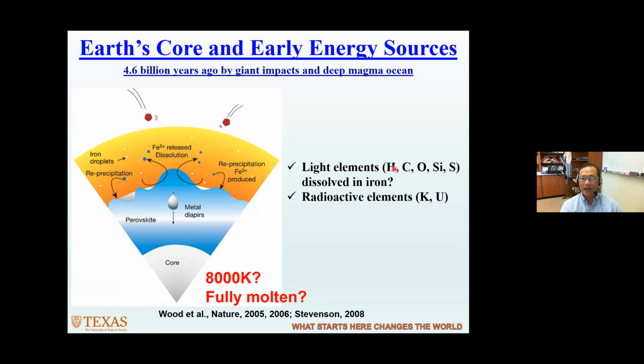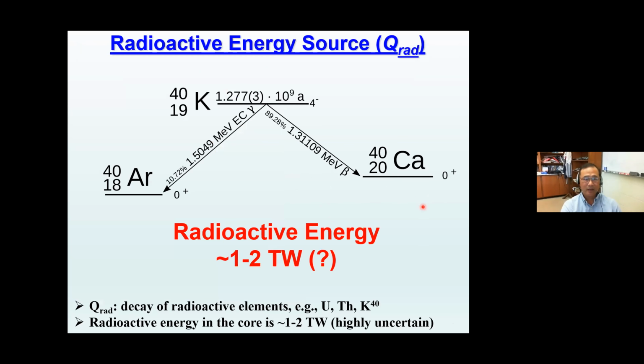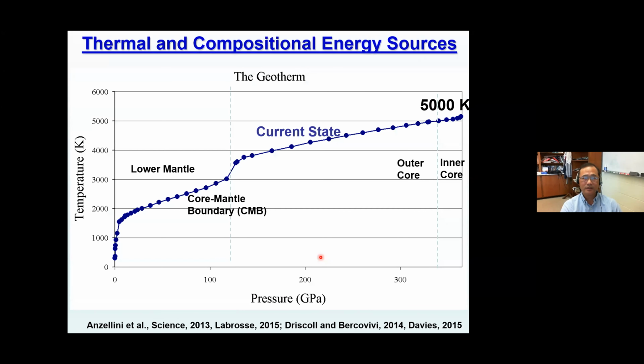Some light elements, such as hydrogen, carbon, oxygen, silicon, and sulfur, also dissolved in iron and went into the core with it. There are also some radioactive elements dissolved in iron, such as potassium and uranium. Those radioactive elements can provide a radioactive energy source to power the geodynamo, probably continuously based on their half-life. The amount of their energy is very uncertain, but it's probably somewhere around 1 to 2 terawatts also.